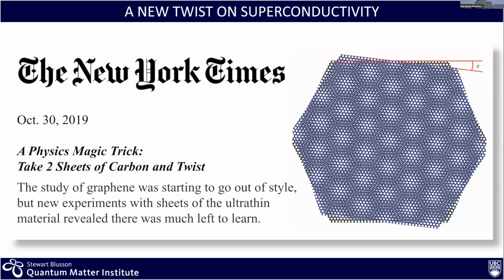What we do, we work on graphene on silicon carbide. So we have an interaction with the substrate, which is very important. And then we use either the substrate from below or the top surface of the interface with vacuum by putting atoms as a way to create either flat bands or other physical phenomena.